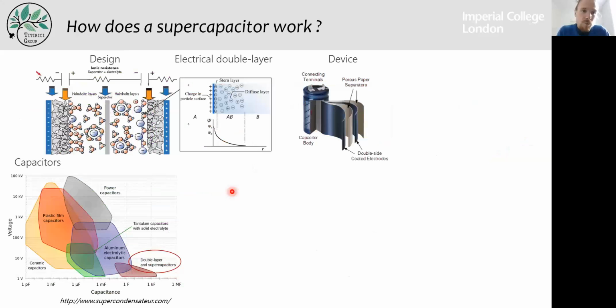So how does a supercap work? As I said, we have 2 electrodes of the same or a different type. It's usually a porous carbon. And upon polarization of your electrodes here, you will observe that your electrolyte ions will store into the pores of your electrode. And here we have a separator that avoids having a shortcut between your positive and your negative side. And here, this is the double layer charging.